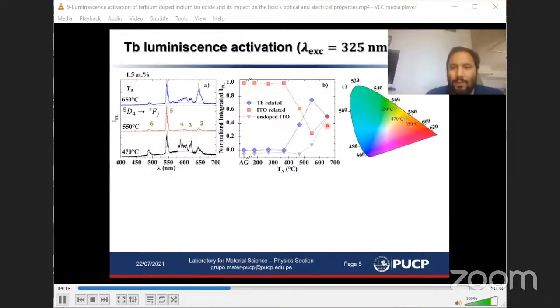For comparison purposes, I'm showing you here the apparent color in this color space, CIE 1931. And we see that for higher annealing temperatures, there is a shift to the red, which is, again, unexpected for terbium ions.